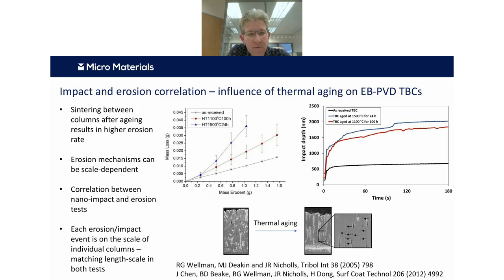So we were interested, particularly, if we could replicate that with our nano impact test. So we chose the conditions where we would have the right sort of probe size, so that we matched the scale of deformation in both tests. We noticed that each event was on the scale of the individual columns. And if you see on the right, you can see, semi-quantitatively, there's a very nice correlation. Now, this is plotted depth against time, so you could easily convert that to impact volume against, effectively, well, I say mass or number of impacts.